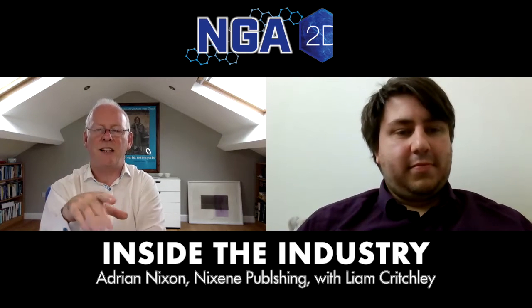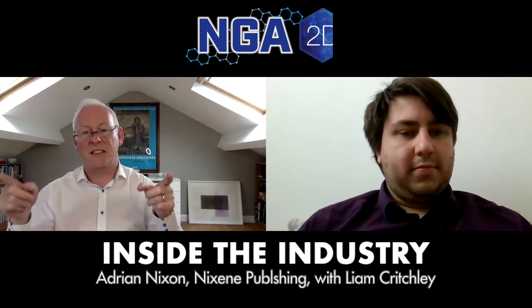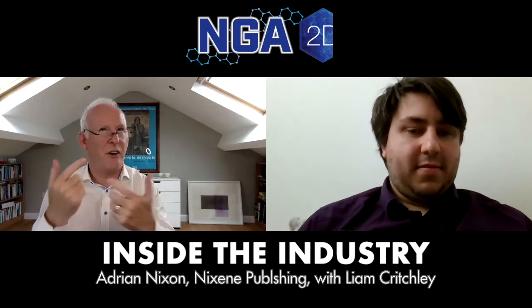So it's tiny stuff. But you and I, Liam, know that about 3 years ago in China, at Peking University, they made something called single crystal graphene on copper foil, like we've just seen, but they made it about 500 millimeters long. So we know that there is a single molecule of graphene that's already been made that long, 500 mil long. So we know it's possible to make single crystal that big, and there's no reason why you can't keep on adding to it and keep on making it. So in principle, there aren't any barriers to actually making this stuff big and fast.